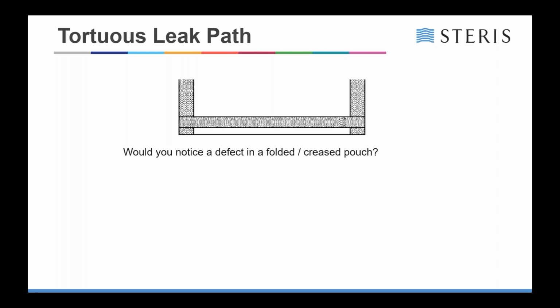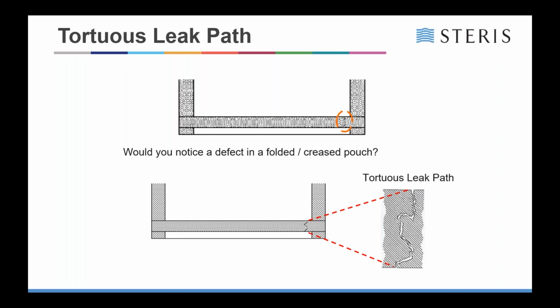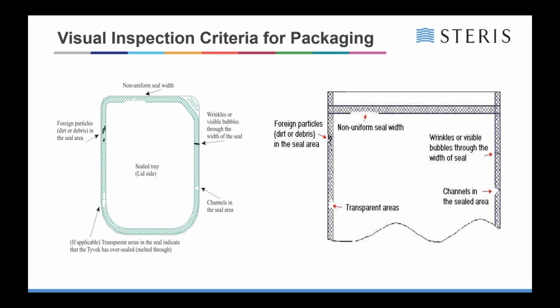This is a representation of a defect that's quite common in pouches and trays, where you get a tortuous path coming through the actual product, which causes a breach in the sterile barrier. As you can see, there's a full breach of the seal here. This is a trace of a drawing of an actual pouch and defect that we found in one of them. What you're looking for with the standard is non-uniform seals, foreign particles or dirt or debris in the seal area, transparent areas where the material is being burnt, wrinkles or visible bubbles throughout the seal, or channels in the seal.